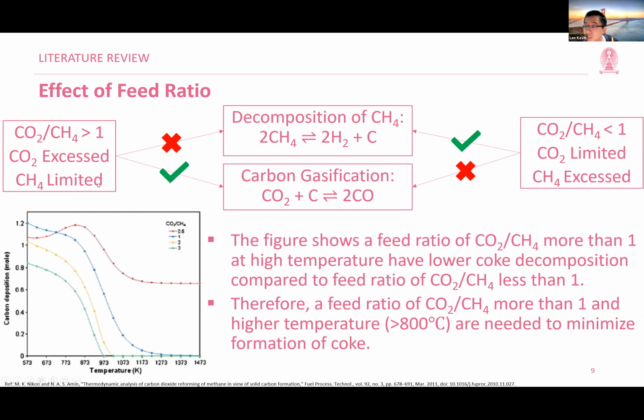The reason for this is at feed ratio more than 1, carbon dioxide is in excess and methane is limited. So carbon dioxide will combine with carbon to form carbon monoxide, reducing carbon. But with methane limited, the carbon formation will not happen. Oppositely, for less than 1, carbon removal would not happen and carbon deposition will happen. So to draw a conclusion for the feed ratio, we can see that a feed ratio of more than 1 and a high temperature is needed to minimize the formation of coke.